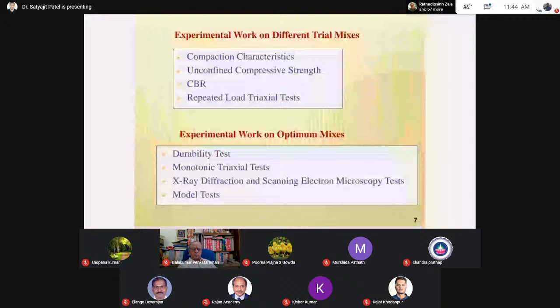Then the repeated load triaxial test or cyclic triaxial test has been carried out to find out the resilient modulus and permanent deformations of the various mixes. Then, based on the above four tests, the optimum mix has been selected, and on the optimum mix the durability test has been carried out, that is wetting drying cycles. Then the monotonic triaxial test to find out the cohesion and angle of friction, which will be useful for the numerical analysis in Plaxis. Then X-ray diffraction and scanning electron microscope tests have been carried out to study its microstructural behavior. Then the pavement model test has been carried out.